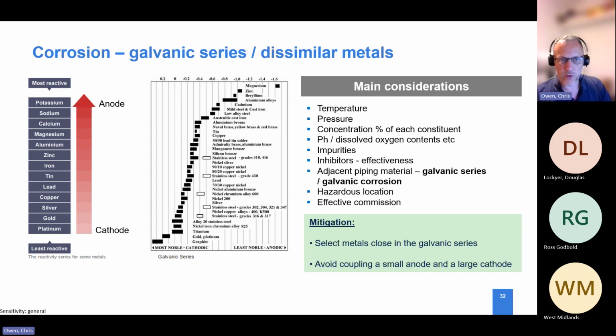The zinc sits more towards the anodic range of the series, so it's going to sacrifice itself to protect the steel, which is not necessarily a bad thing, because the zinc corrodes at a much slower rate. The zinc oxide which is produced is not as harmful to an installation as the iron oxide from rust. So the zinc sacrifices itself to protect the carbon steel. And then if there's stainless in the system, the stainless steel basically protects itself by having everything else below it sort of accelerate in terms of corrosion.